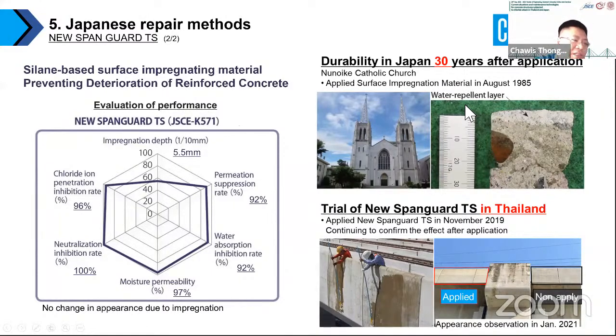The performance table is of the New Spanguard TS based on the method of the Japan Society of Civil Engineers, which we call JSCE. The results show that it has a high penetration suppression rate for water, chloride ions, and carbon dioxide, compared with the non-coated concrete specimen. This is a project reference in Japan showing the product durability of more than 30 years. We confirmed that the water repellent layer was still effective. We have also tested a mock-up in Thailand, as well as a parapet structure and somewhere else in a train station under construction.